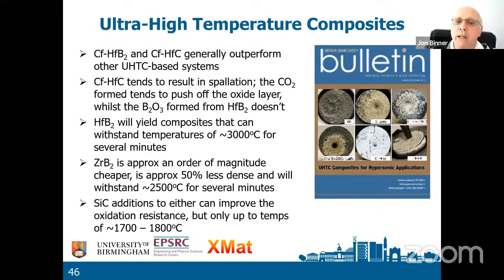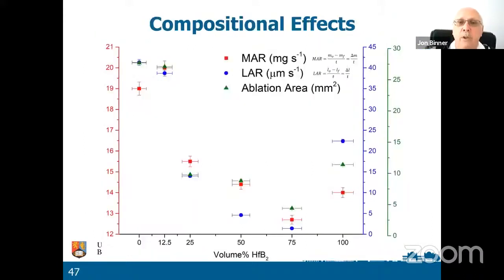Zirconium diboride will go to about 2,500 degrees centigrade for many minutes. It is a lower temperature material, but it's half the mass and is a whole order of magnitude cheaper. So if you don't need the 3,000, if 2,500 will do, then you want to use zirconium diboride. Silicon carbide additions can improve the oxidation, but only up to relatively modest temperatures.